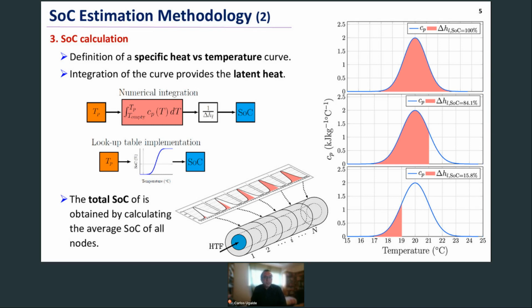For example, what these graphs are telling us is that at 19 degrees, the state of charge would be nearly 16%, which is shown at the bottom graph. Whereas for 21 degrees, this would be around 84%, which is shown at the middle graph. Whereas for 24 degrees, this fictional battery would be fully charged, which is shown at the top graph.